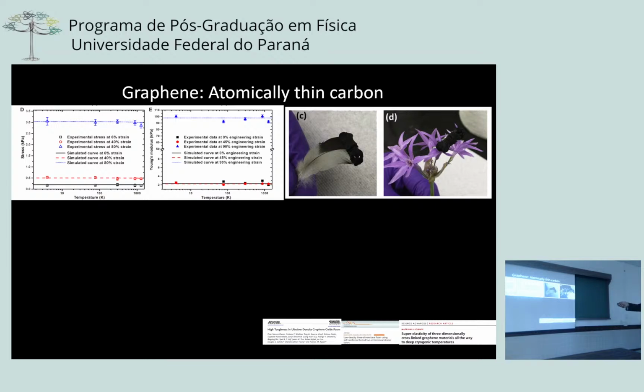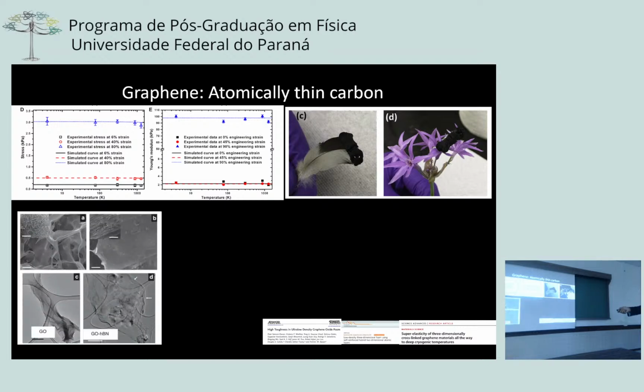And if you see the stress level or Young's modulus, they are almost constant throughout the temperature range. Now this interconnected, covalently structured porous material made of graphene will have the same strength all throughout the temperature range. And that becomes very exciting, and we can start utilizing this material for a universal application which is independent of temperature.